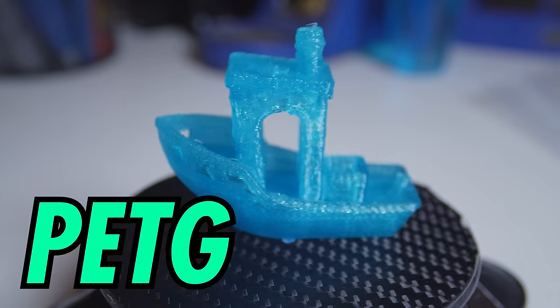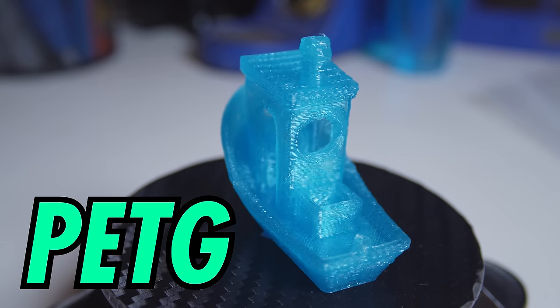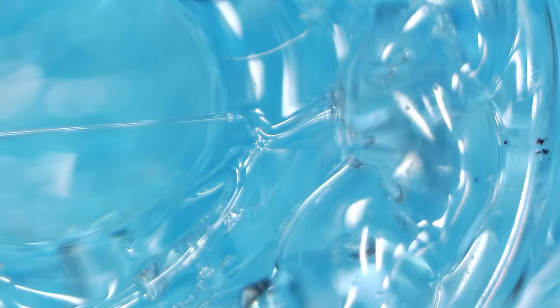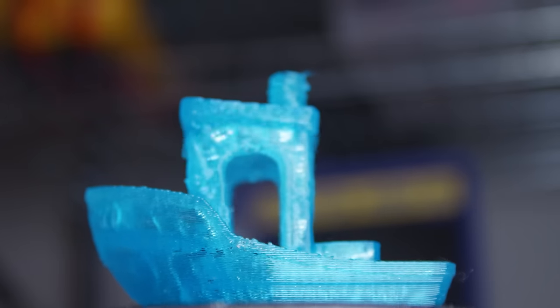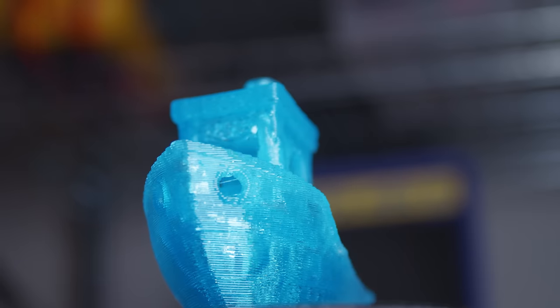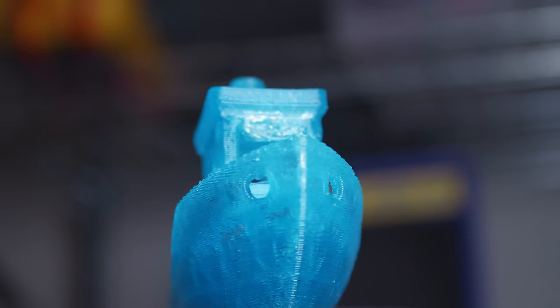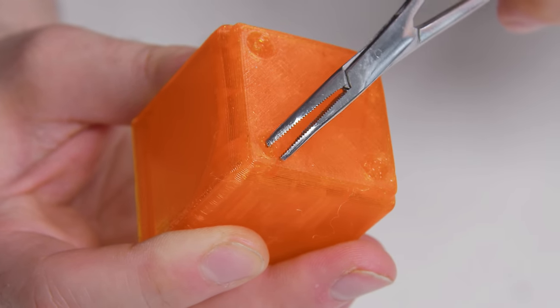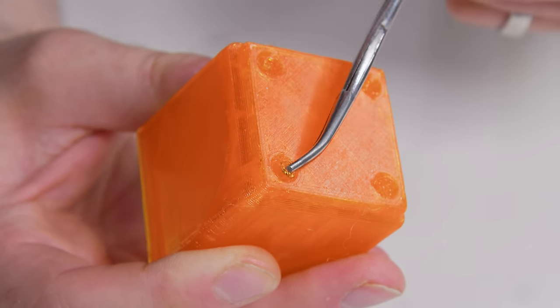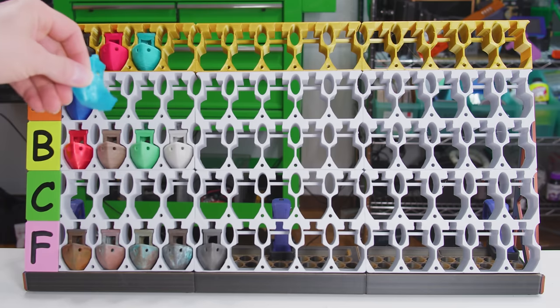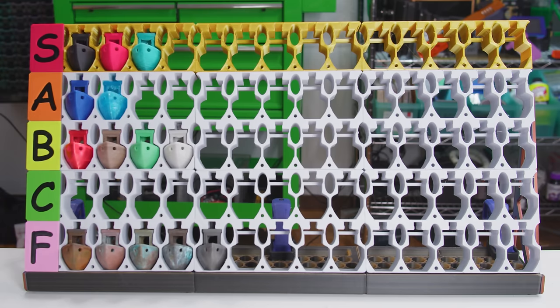Next up is PETG, and this is the opposite. Supremely versatile, never really exceptional. This stuff is a little bit harder to print than PLA, but it's tougher, it handles higher temperatures, and it generally survives a lot more real-world punishment. PETG is also one of the most transparent polymers, and has one of the lowest coefficients of friction. You can get clear, slicker filaments, but they are way harder to print. PETG does have problems, especially when it comes to overhangs. Bridges will just sag like crazy, and supports won't release. It's not very difficult to design around this, but if you're mostly printing other people's models, PETG can cause more harm than good. It also absorbs water pretty fast, so the more humid your climate, the faster you want to finish a spool. PETG belongs in A tier, a step up from PLA.